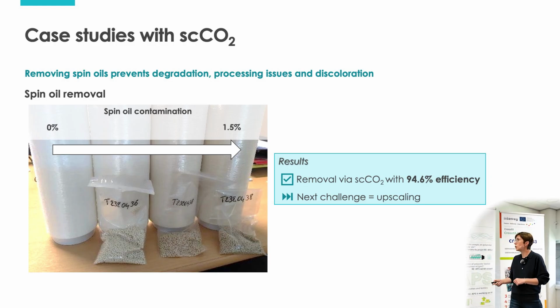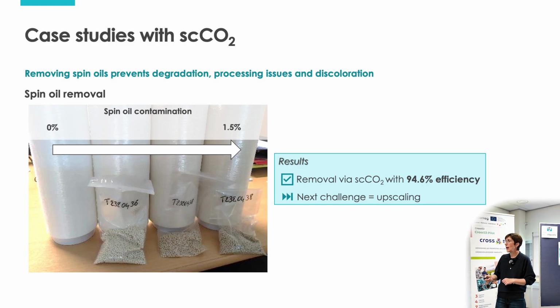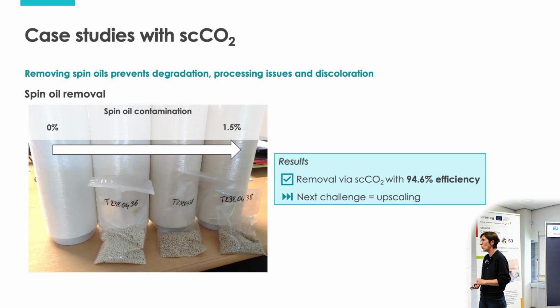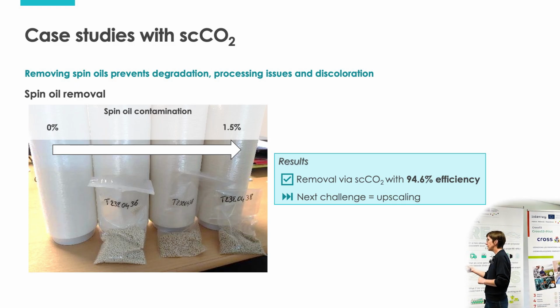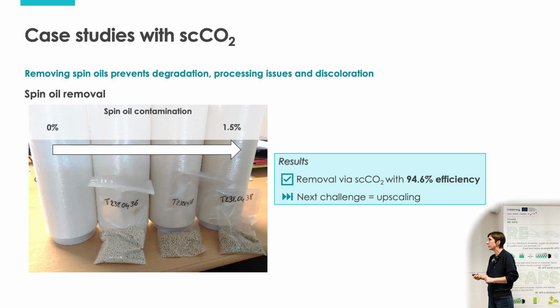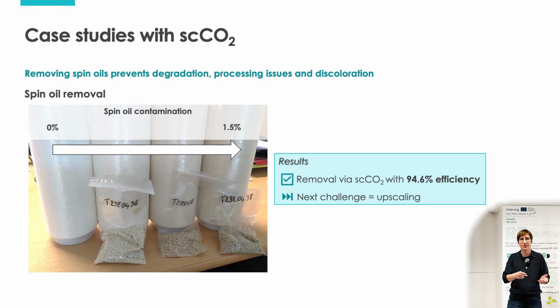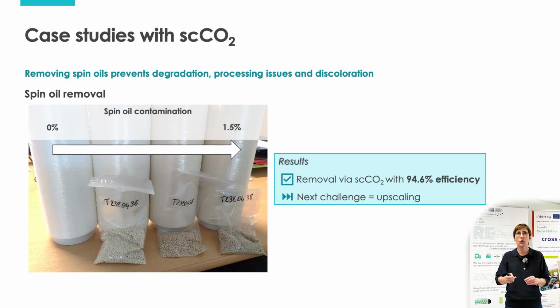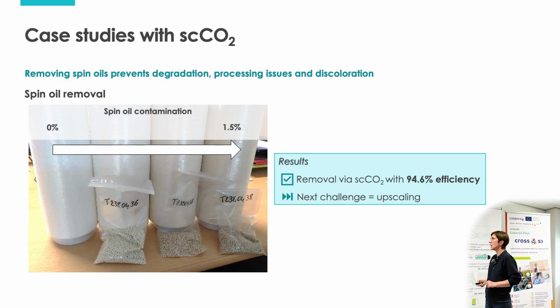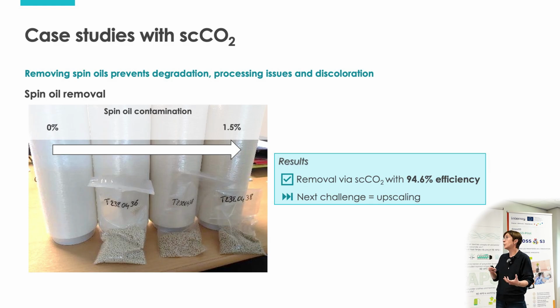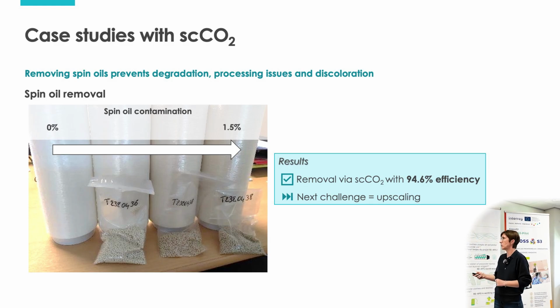What we then try to do is use supercritical CO2 as a kind of pre-treatment to remove the spin oils, and up to 95% of the spin oils could be removed. So with this you can go back to a white virgin polyester grade instead of something that is a little bit yellowed due to the pre-clean. So the next thing is to try to upscale this to really industrial scale to make sure that we can also prove this on an industrial scale.